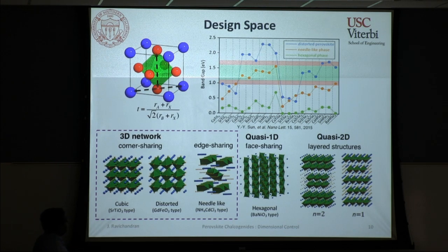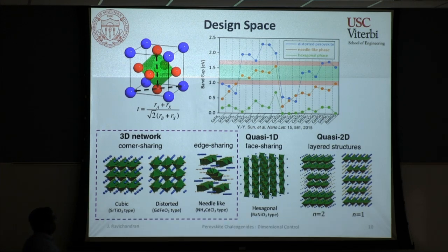same perovskite structure and try to focus on a narrow set of compounds for this specific talk. So the ones that we are interested in are early transition metal based systems, which means your B side has titanium, zirconium, and hafnium, and your A side has calcium, barium, and strontium, and your X side is sulfur and selenium. Okay, so it turns out these materials can assume one of a few different types of crystal structures that are shown here. That allows you to have the octahedral connectivity show very specific dimensionality, and that's what we're going to leverage in this specific talk and show that light can interact very differently when your octahedral connectivity is very, very different. Okay, and that gives rise to various different interesting applications.